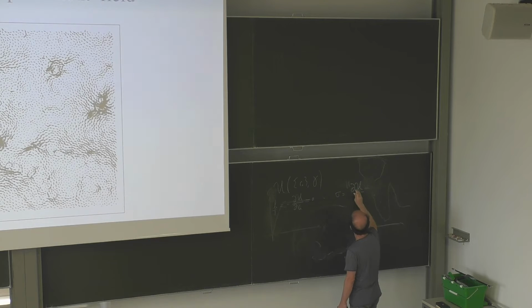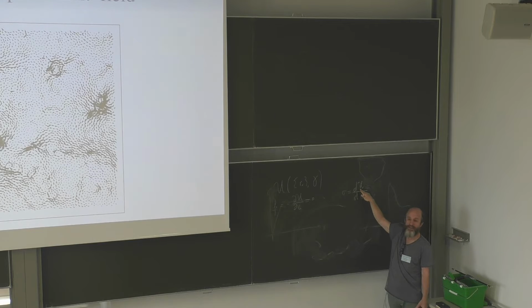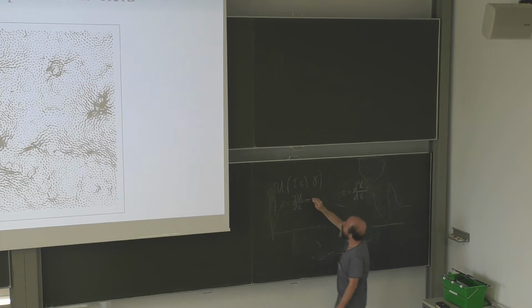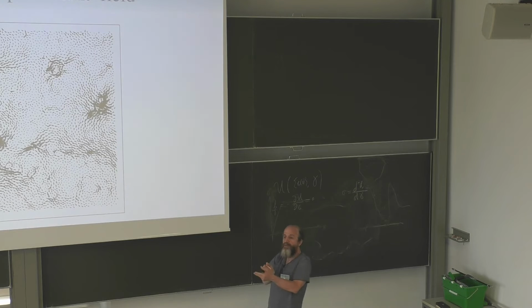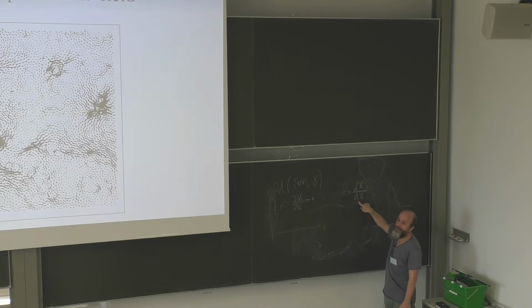is, of course, the derivative of the potential. I will introduce a total derivative, which means that I derive the potential along the path of the local minimum. When I say this, I'm saying that these non-affine parts of the position depend on strain when you follow the local minima. So if I shear, my non-affine part of the position will slightly vary in order to guarantee minimization. So stress is the derivative of the potential. The total derivative I write here means that I follow mechanical balance.